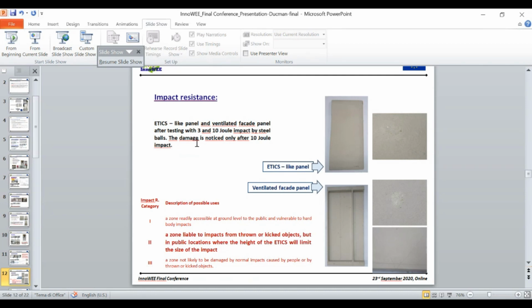And damage is noticed only after 10 joule impacts. Nothing happened with 3 joule impacts. So it means that this material belongs to category 2, because certain damage has been noticed after 10 joules. But it means that the panels can be used for a zone where there is a limited size of impact. So if there is heavy traffic, then it's better if it's category 1.